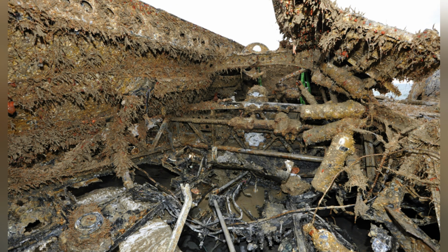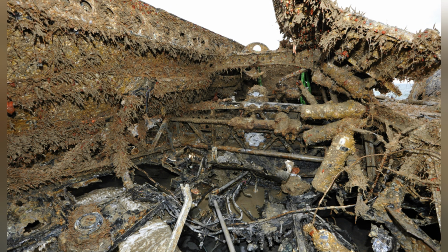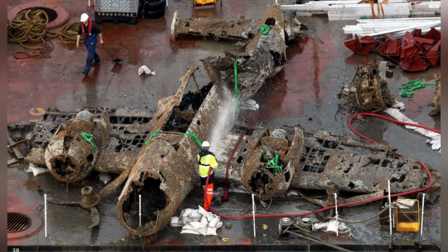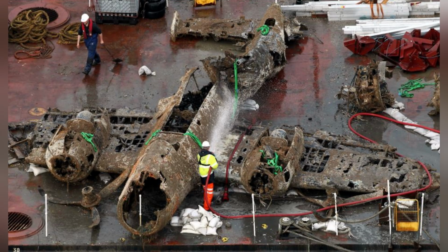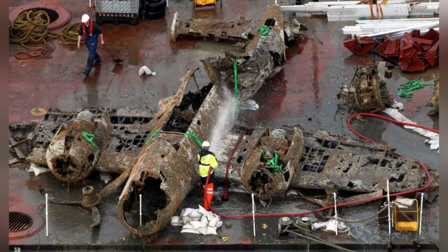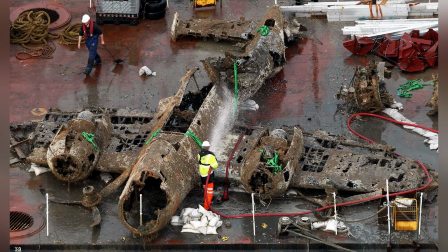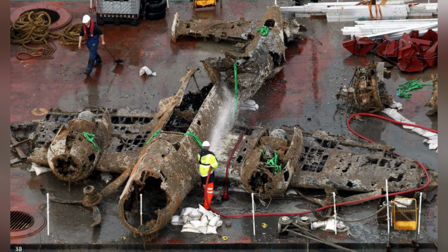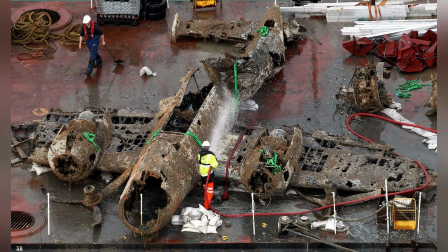The result is exfoliation, where the metal flakes apart in layers, destroying the structural integrity and the historical surface. This is the chloride trap. The act of recovery triggers the destruction of the object unless a specific chemical countermeasure is applied immediately.